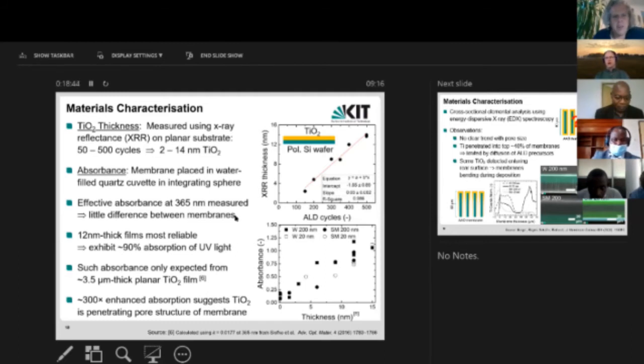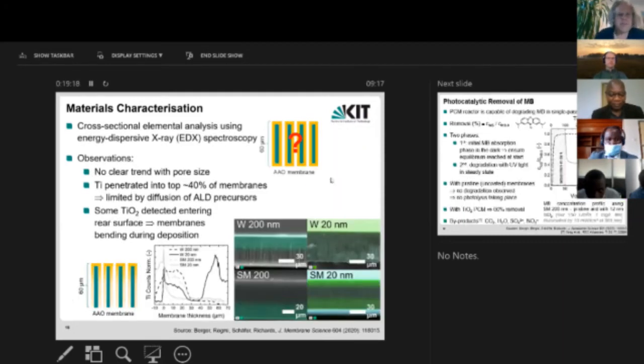And that's why we used this method of putting the samples inside the integrating sphere. We were able to determine that, because of the structure of our membrane, we're getting typically the amount of light absorbed that you would expect from a 3.5 micron thick planar film. That's 300 times thicker than what we actually have. So this was the first evidence to us that the titanium dioxide is probably inside the membrane, and light is being scattered around and therefore much more effectively absorbed than you might think. And that's what we then started investigating next.